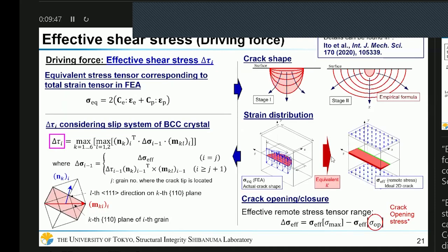And the effective shear stress is a kind of driving force in this model. But the evaluation process of this parameter is a little bit more complicated, so I will show you only the outline. First, we evaluate the equivalent stress tensor, which corresponds to the total strain tensor obtained from finite element analysis. And considering the effect of the crack shape, strain distribution, and crack opening-closure behavior, we evaluate the effective stress tensor range. And then, considering the slip system of BCC crystal, we evaluate the effective shear stress based on these expressions.